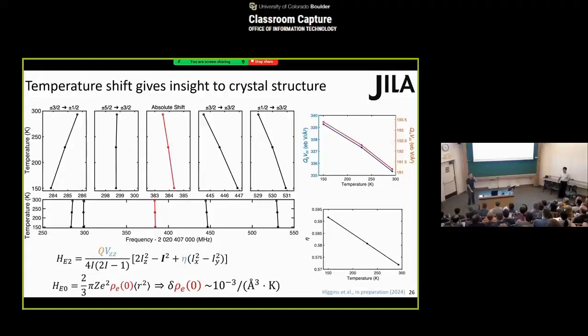Yeah, so essentially we think the 300 kilohertz is the actual spectral feature we observe in the experiment. We think that's more an indication of our laser linewidth being about 300 kilohertz, but the underlying transition is narrow. The transition lifetime is about 600 seconds, so a very long, very narrow transition, but we could also still have inhomogeneous broadening in the crystal field, which we don't know exactly yet. There are theoretical predictions saying that this should be on the order of a few hundred hertz to kilohertz level. So likely we're not seeing this crystal-limited inhomogeneous broadening yet.